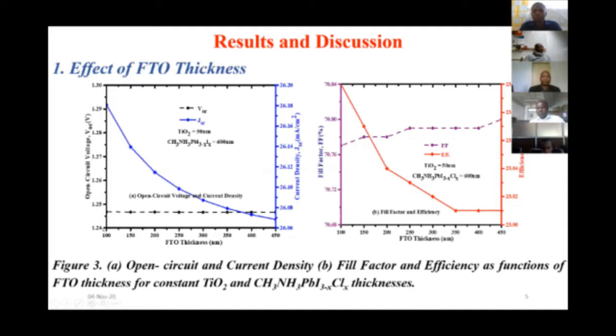We were varying our layer thickness, FTO, from 100 nanometers to 450 nanometers. And one thing we realized from the results is that the open circuit voltage remained constant, while the current density decreased as we increased the FTO thickness.